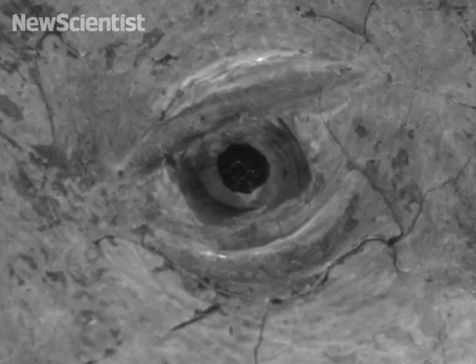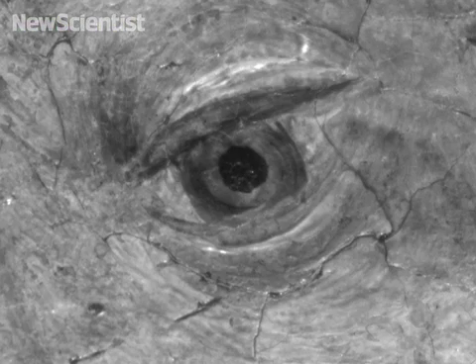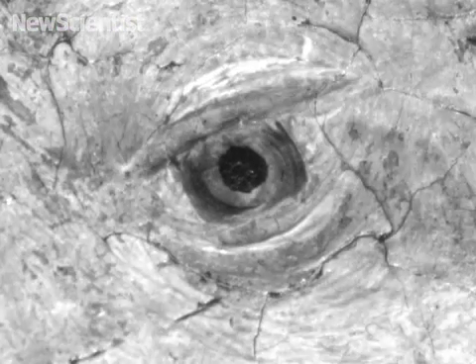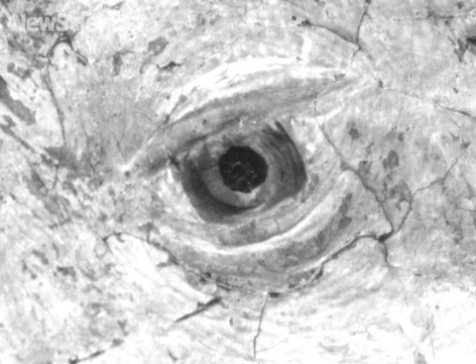We can also probe into the near-infrared, where a lot of the paint layers become transparent, so you can reveal the preparatory drawing that might have been done. So far, the analysis has revealed detaching paint from an area retouched during a conservation effort. Based on this scan, it also seems like the artist didn't draw an initial sketch.